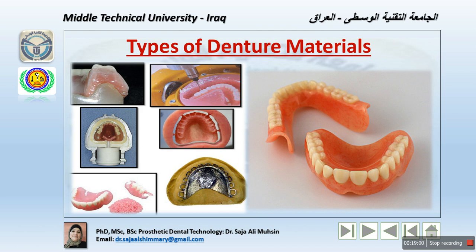In terms of 3 hours, the polymerization will be gradual up to 74 centigrade, and then for 1 hour or 1 hour and a half at 90 centigrade, or the long curing cycle, the overnight cycle, or 8 hours, letting the curing proceed at 74 for 8 hours.